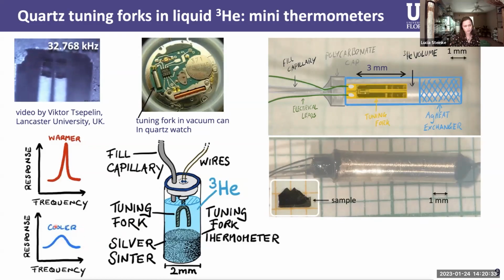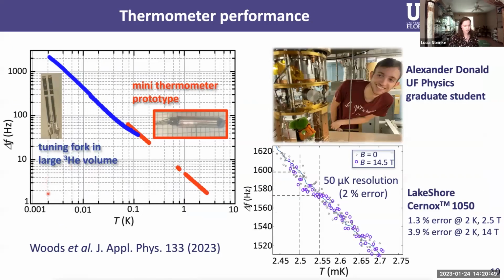So then if you look at the tuning fork response versus frequency, you see a very damp resonance. And at higher temperature, you have a sharper resonance. So looking at the width of this resonance, we can use that as a measure of temperature. Now let's put these prototypes that we built to the test to see if they're actually good to measure temperature.